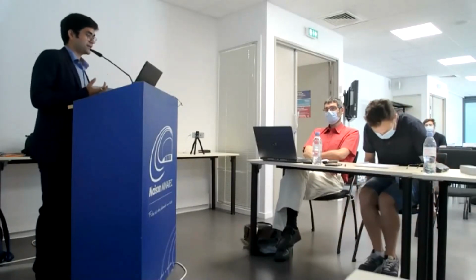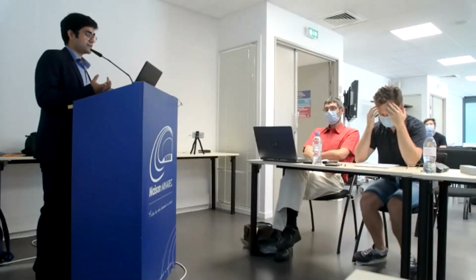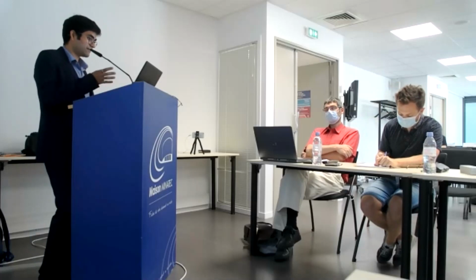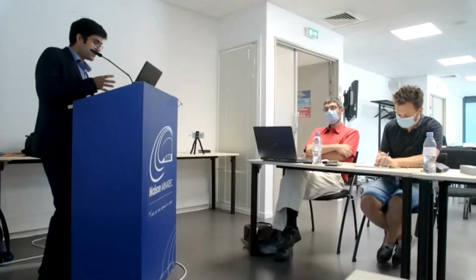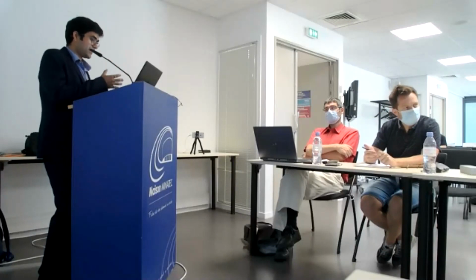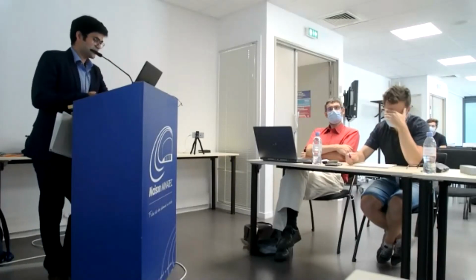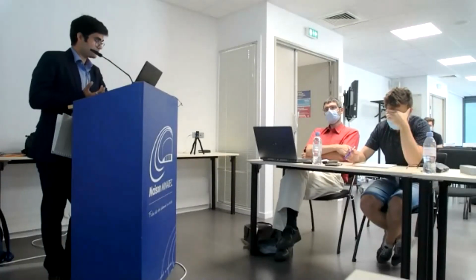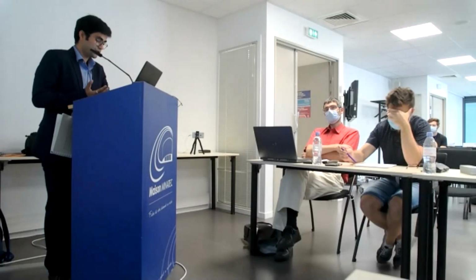Yeah, true. In fact, we haven't really worked on the cellular automaton model to predict the microstructures. It was just a thought that if we are able to reliably predict microstructures, for example with zirconium addition, we can estimate a microstructure based on L-PBF conditions. We can have a reliable criterion, and if we incorporate the RDG model into the cellular automaton model, we can estimate the real pressure drops along the grain boundaries, for instance. So that is my idea, but I do not have many details about this cellular automaton model, to be honest.